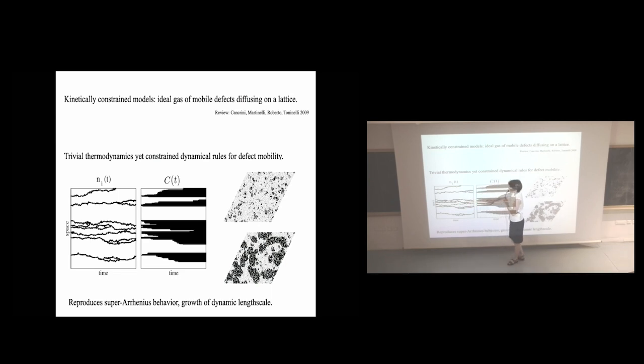And if you look at what happens for the dynamics, essentially, these black regions correspond to the trace of where this mobility defect has been. So essentially the mobility went through this region, so you can imagine it rearranged the liquid. In terms of my simulations, it went from blue to red, so it has a different structure. Here, the blue corresponds to the regions that are still in the same structure as at time zero, and the black regions have moved. So you see that what you look at in the dynamics corresponds to the trace of where the mobility has been. You have a point moving in space, and it draws a domain of a given size, and this is the origin of the domain.